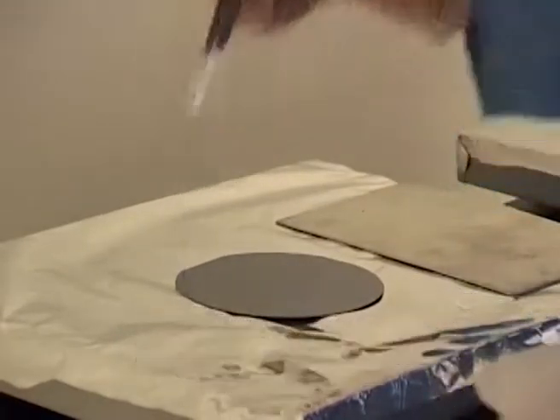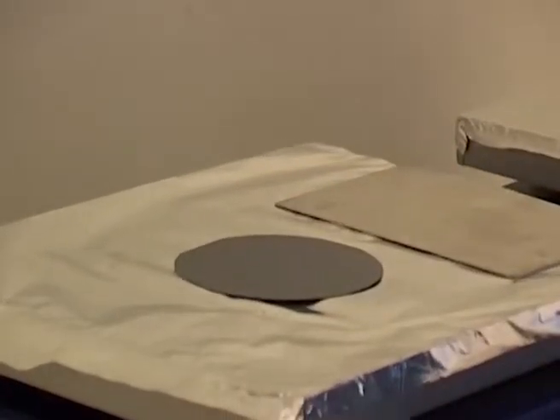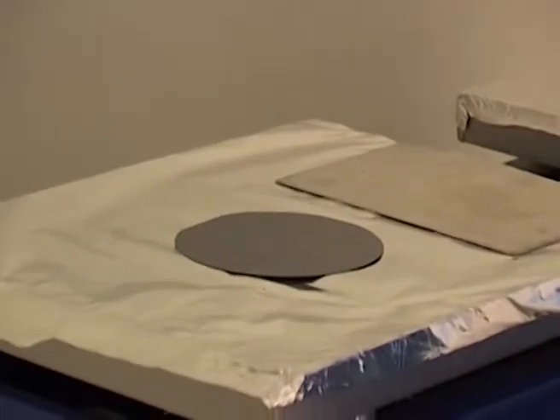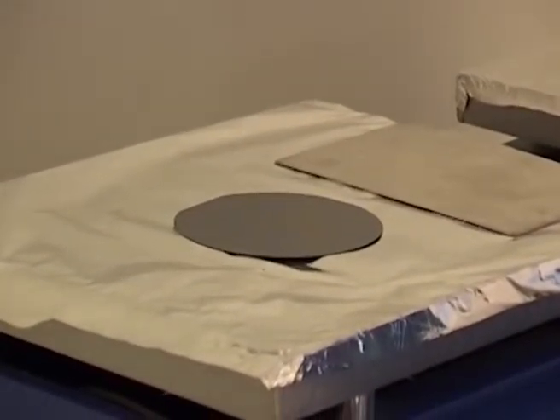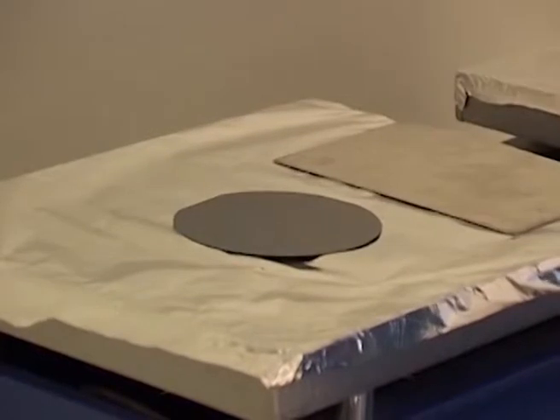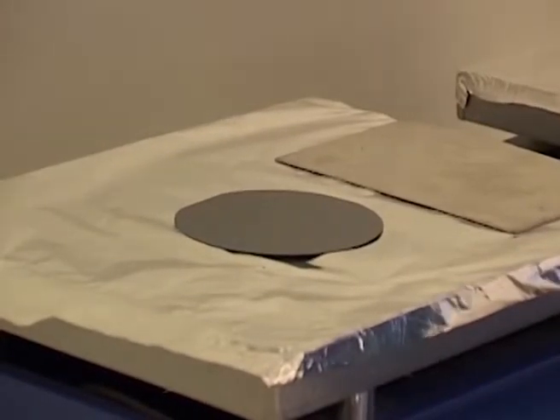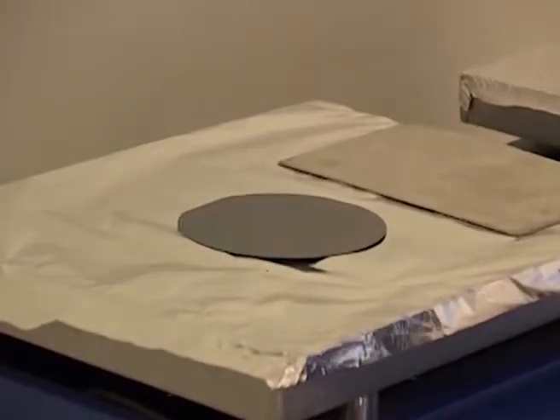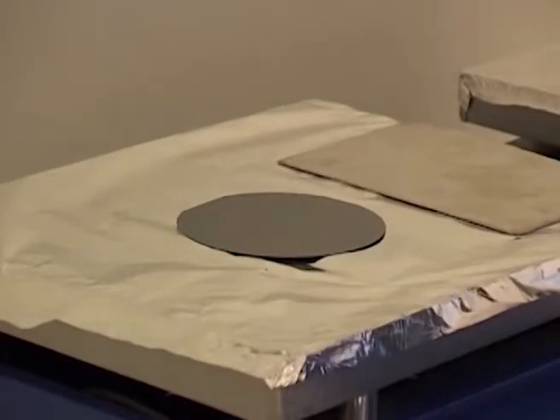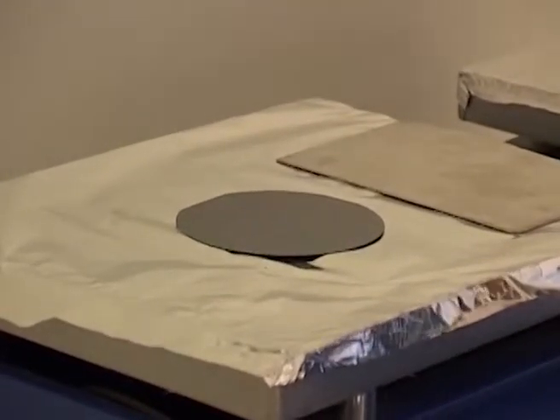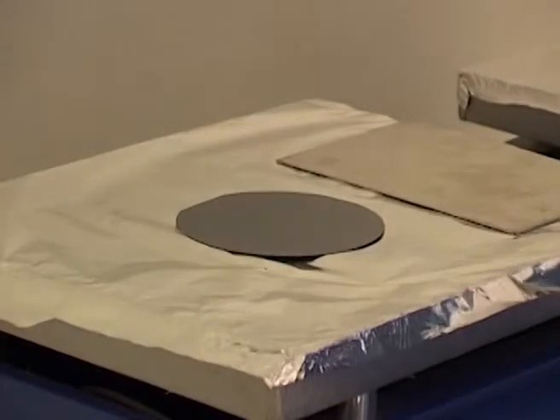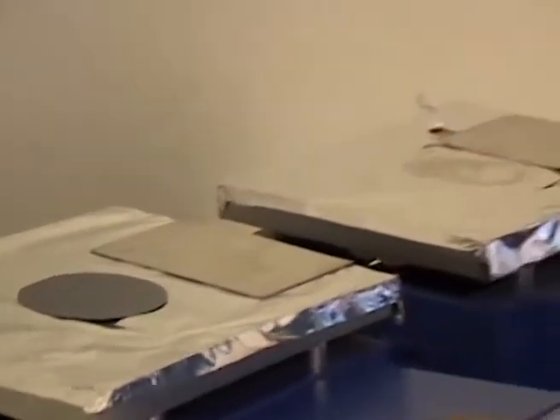At this particular stage, we would like to operate the stopwatch by setting it at 3 minutes and then starting it, and basically the idea is that this will give an alarm at the end of 3 minutes. We need a 3 minute heating time for this particular process step at 65 degrees, and then we will go to the next step, which is another 3 to 4 minutes on the 95 degrees.